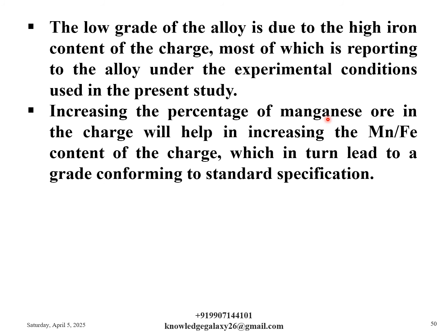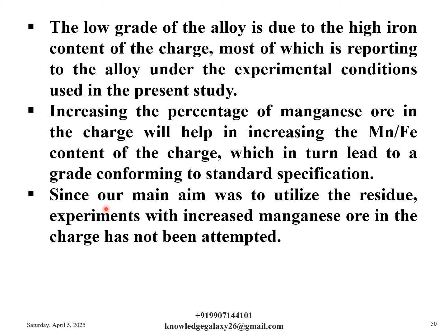Increasing the percentage of manganese ore in the charge will help in increasing the Mn by Fe ratio of the charge, which in turn leads to a grade conforming to standard specification. Since our main aim was to utilize the residue, experiments with increased manganese ore in the charge have not been attempted. An alternative material has been tried instead to enrich the manganese content, and the details are given in the next slides.